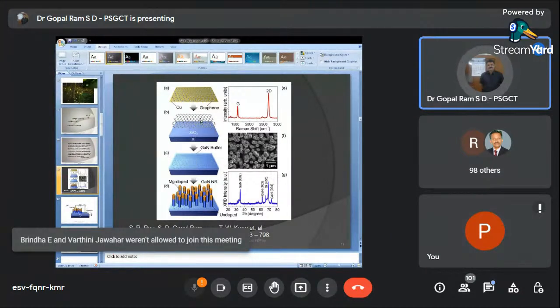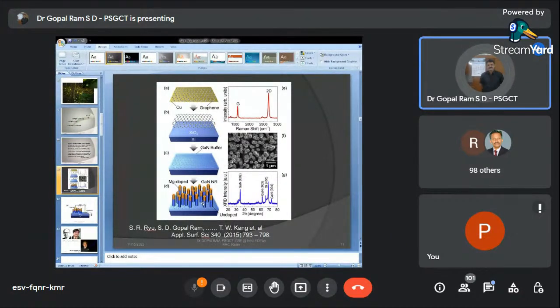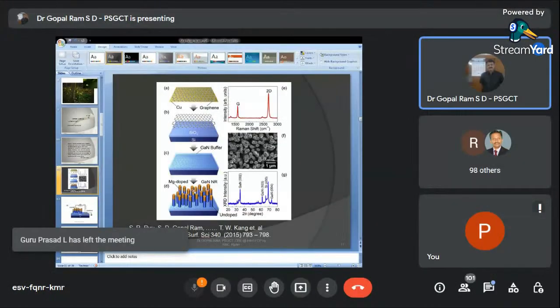You can see these hexagonal patterns there. Otherwise, usually sapphire would be used there, or some aluminum nitride layers would be required to initiate the nucleation of this gallium nitride. The compound gallium nitride cannot be formed very easily by a simple chemical reaction. For example, if you want zinc oxide, we need just oxygen and zinc metal. They would react and form zinc oxide. But in this case, nitrogen is an inert gas. It cannot directly react with anything, and this compound cannot be directly formed.